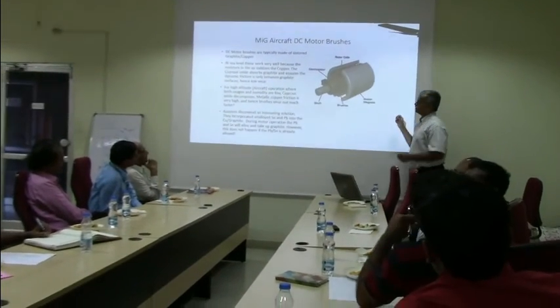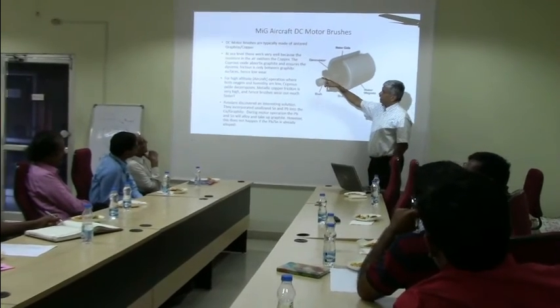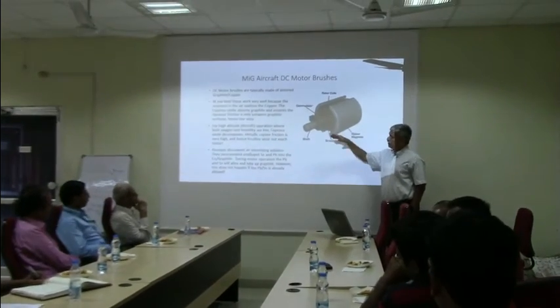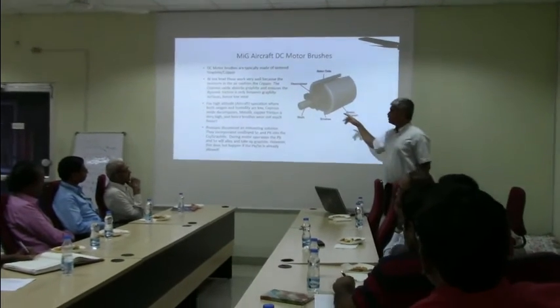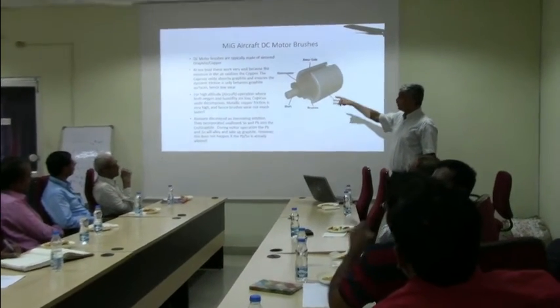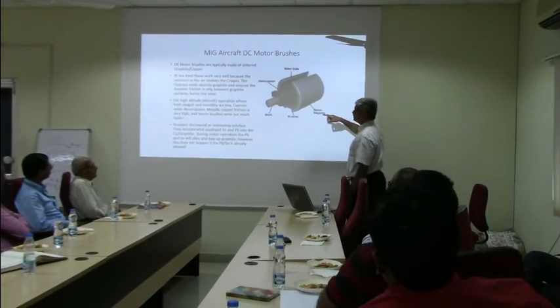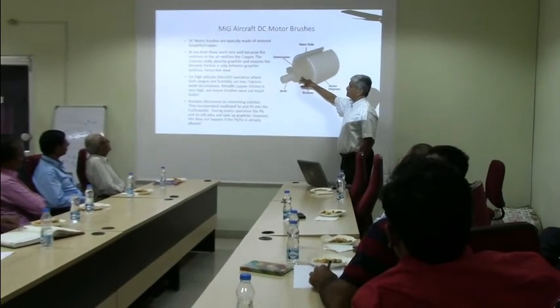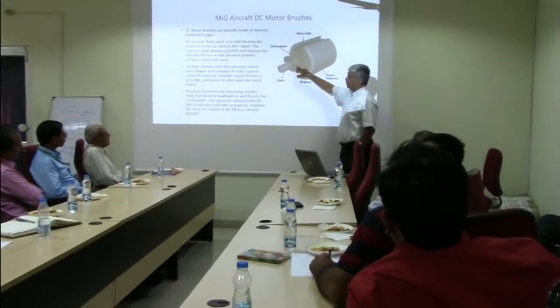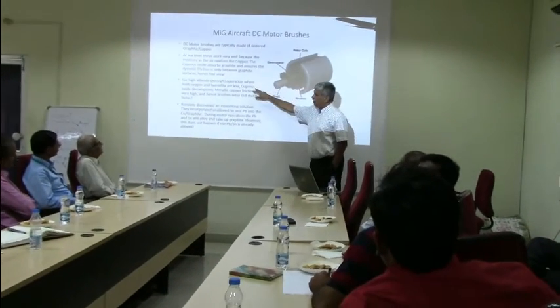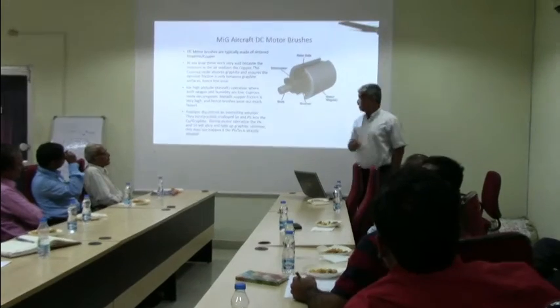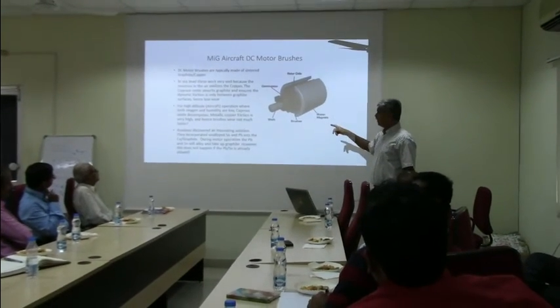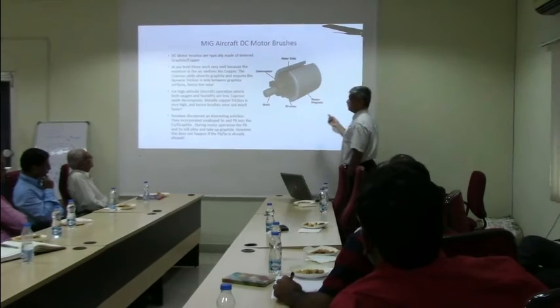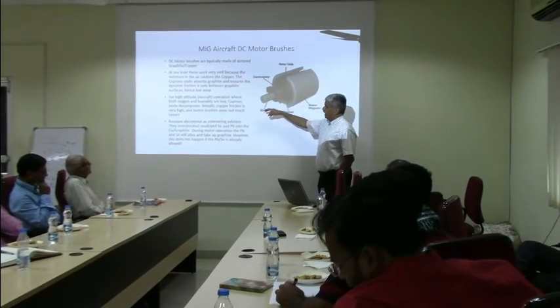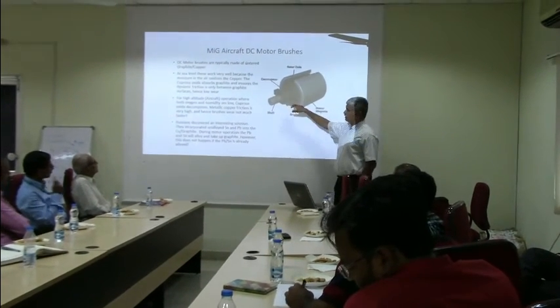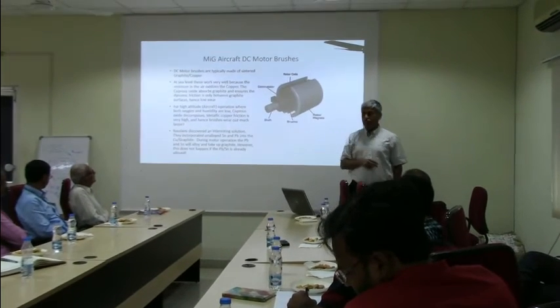And there's a trick to it, which is that the copper forms an oxide at sea level because there is moisture in the air and so on. The cuprous oxide absorbs graphite and ensures that the dynamic friction between the graphite surfaces is low, and therefore there is low wear. But once you put this in aircraft and you're flying at high altitude, both the oxygen and the humidity are low, and therefore this cuprous oxide is an unstable oxide. It decomposes and you start getting metal copper-copper friction, which is very high, and the brushes end up wearing out much faster.